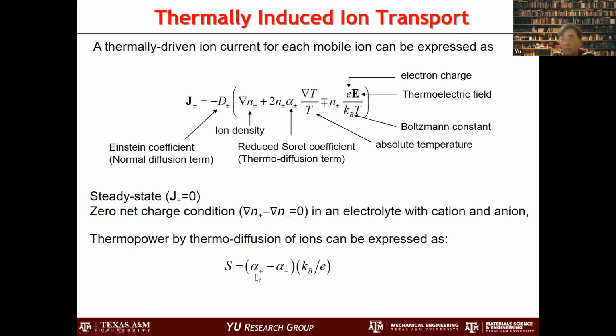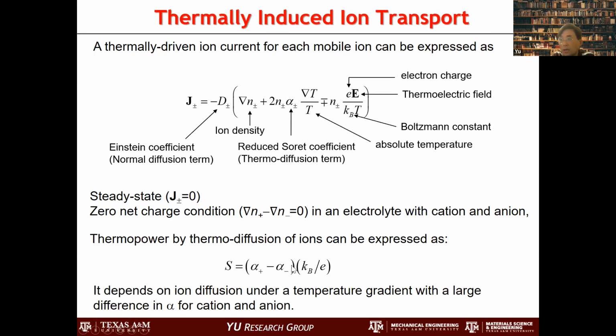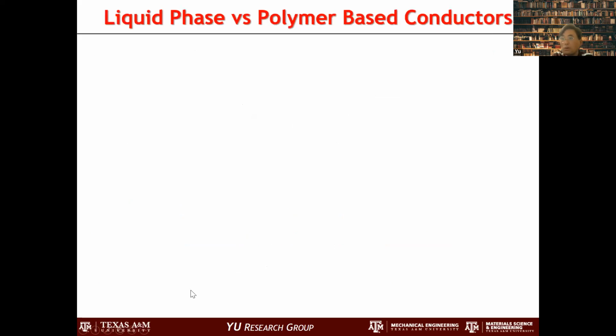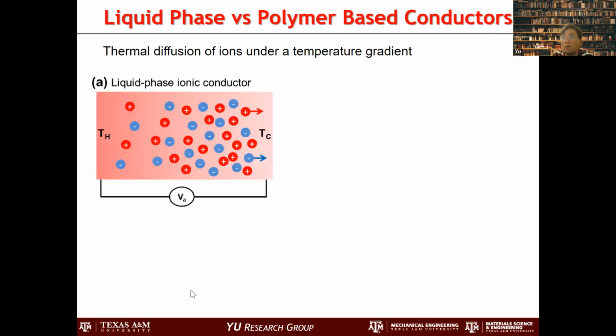That is proportional to this alpha factor, which is called the Soret coefficient. For positive ions and for negative ions, the Soret coefficient doesn't mean it's always a positive or a negative number. So whatever those numbers are, the difference is supposed to be greater to get a large S value. So that was our motivation: to make those two far apart, and typically those alpha values are positive numbers. So we try to make one parameter as small as possible. That was our approach. So we actually tried many different materials at that time.